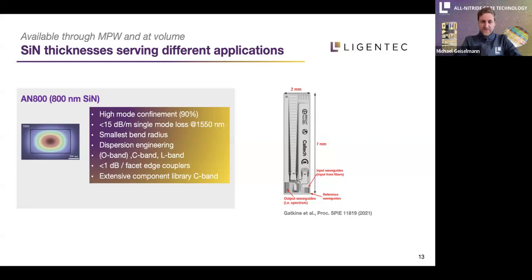The PDK is available for C-band, where we have an extensive component library, including below 1 dB facet edge couplers, but you can also design components in O and L band, and even further, as I show afterwards. So here, an example to the right is a circuit of AWGs that was used for a spectrograph. So you can put your design in a very compact, here 2x7 millimeter, chip.